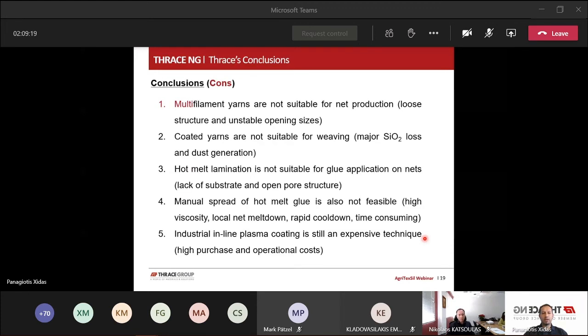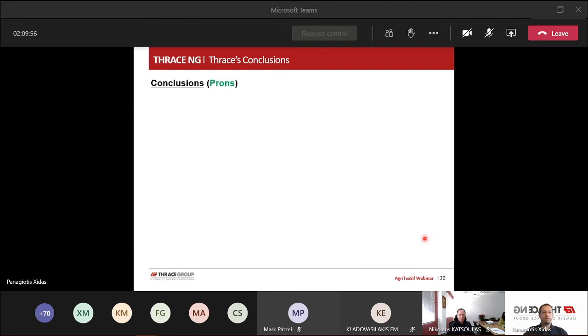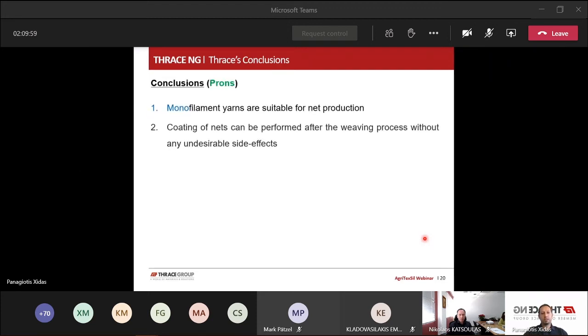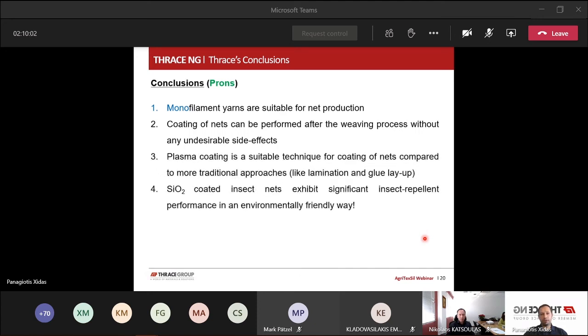The effort for manually spreading hot melt glue is also not feasible because of the high viscosity of the glue, the rapid cooling down, the local net meltdown, and the time consumption of the whole process. And industrial inline plasma coating is still an expensive technique because of the high purchase and operational costs. I'm expecting that in the next few years, the technology will move ahead and the cost will be significantly reduced. The positive conclusions from our work are that monofilament yarns are suitable for net production.